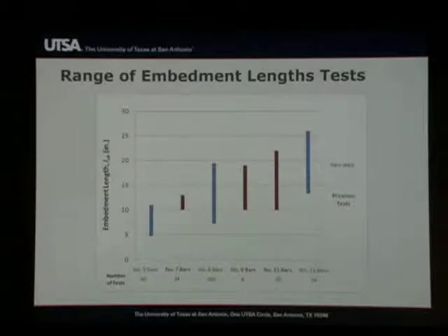The last parameter is the embedment length, and we see also that with the use of larger bars, increasing the population of number 11s, and also increasing the yield strengths of the steel that we're evaluating in these tests, then the range of embedment lengths went up significantly as well.